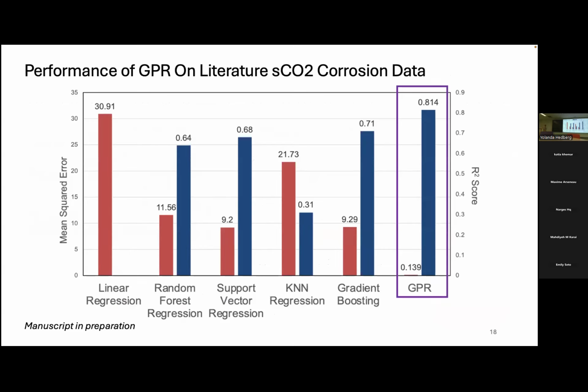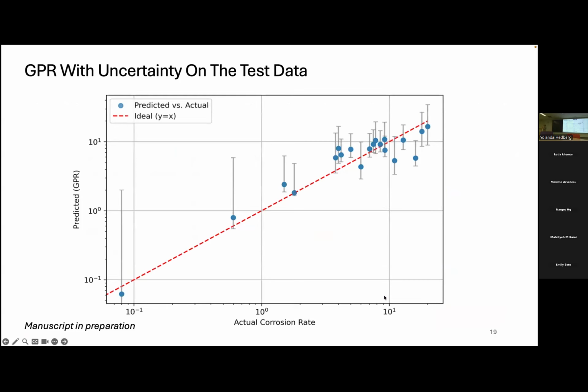So Prince has tested out that if you are going to use a Gaussian process on the literature data set, so he has curated some, say, manually curated data sets onto these, and the Gaussian process actually works at least on par or better than other kinds of models. Another thing that the Gaussian process model can tell you is that if you are going to predict the corrosion rate of your, say, supercritical CO2 corrosion, it has an error bar about the predictions.